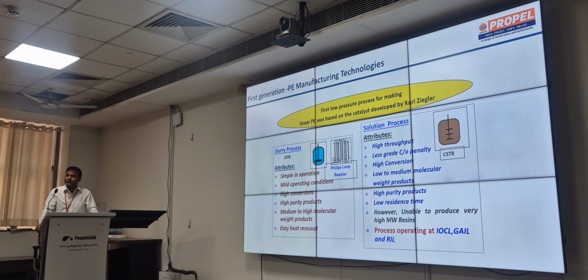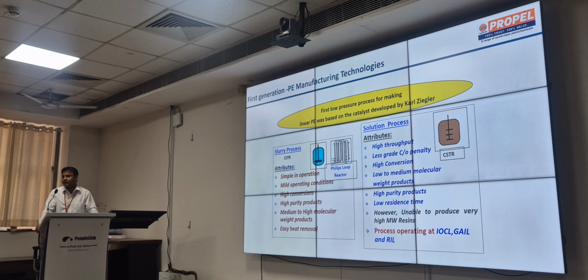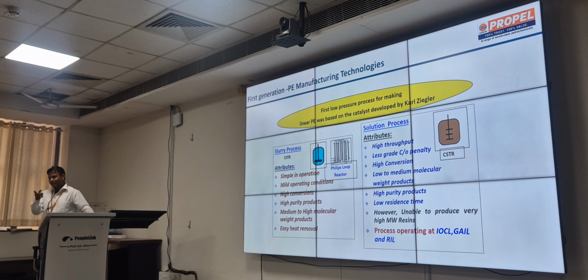But the drawback with this process is that you are using solvents like cyclohexane. So you need to add different separation steps to remove this cyclohexane. In fact, even at the extruder where you pelletize the product, about 2% cyclohexane is still available. So for applications where you need organoleptic properties, there is a concern about the odor, just like this bottle.